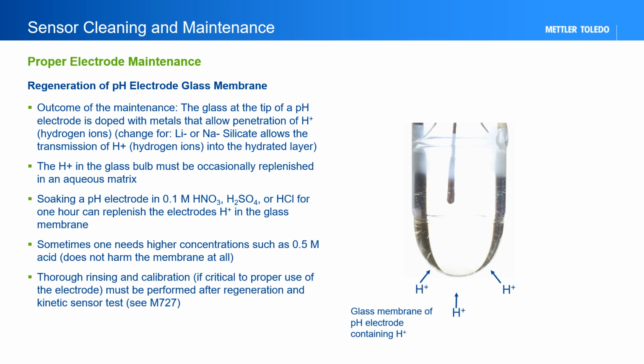Similar to the slow recharge of storing a pH electrode in a pH 4 buffer, a stronger solution can be used for more powerful recharging. Stirring or storing the electrode in a solution of approximately 0.1 molar acid can thoroughly recharge the bulb. It is very important to thoroughly rinse the electrode with DI water after recharging and perform another calibration if calibration is needed for proper use.